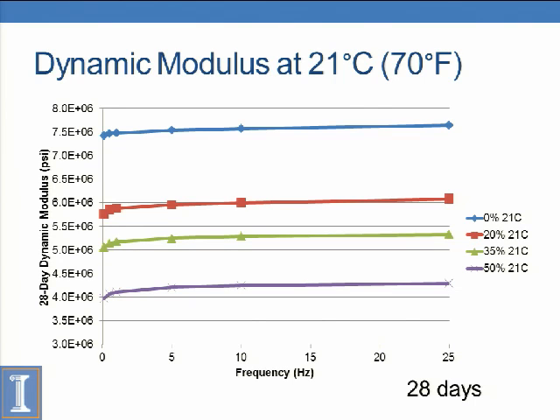Probably. Actually, we looked into that, and that's not true. But we didn't look into the dynamic modulus. Yeah, we did, only at minus 15 Celsius. But you probably won't see the effect at minus 15. Oh, I see what you're saying. Yeah. I mean, if you test, let's say, dirty RAP at 21 with 3.3% asphalt content in the fines especially, because most of the asphalt is carried by the finer portion of your RAP. The coarser portion doesn't carry that much asphalt content, so the finer carries the even higher percentages of asphalt.